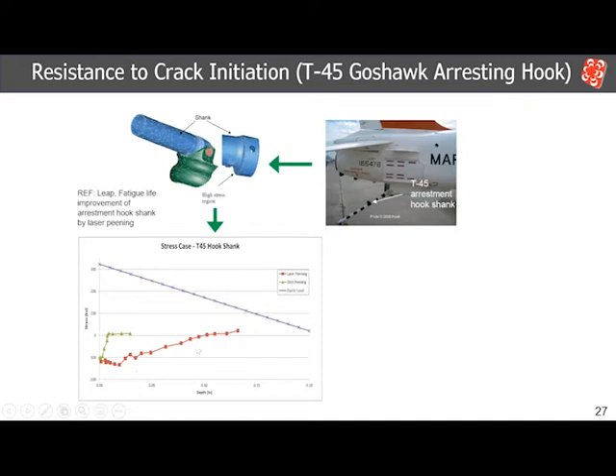Two surface treatments were investigated here: laser peening and shot peening. A very important aspect of how to quantify the benefit from a surface treatment that is generating compressive stresses is what's called a superimposition. Simply speaking, you have the tensile stresses being applied minus the compressive stresses that you're generating from the surface treatment. Using that concept, you can see the two lines. This one is for the shot peening, and this one is for the laser peening. And these are the actual stresses being experienced by the material.